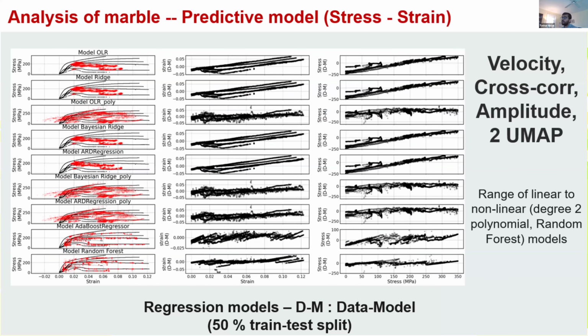And then finally, we put it all together and we use the UMAP to do that hard task. We've added a couple of UMAP features, and we start to get a lot more accurate predictions for the full stress strain curve. So you're predicting the stress and the strain based on just the time instantaneous velocity, cross-correlation, amplitude, and UMAP features of the waveform. We can get a lot more accurate predictions of the rheological state, the stress strain state of the system. And again, this is only showing it with 2 UMAP. If we add a few more, the accuracy starts to increase even more as it captures more of the aspects of the waveform structure overall.